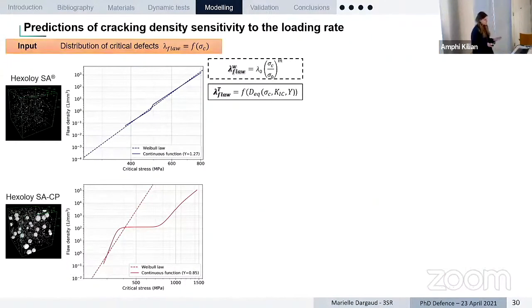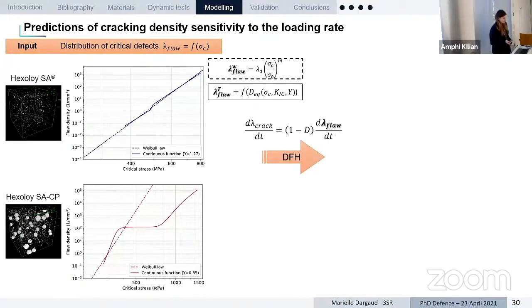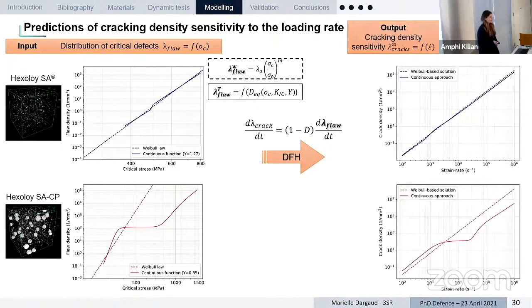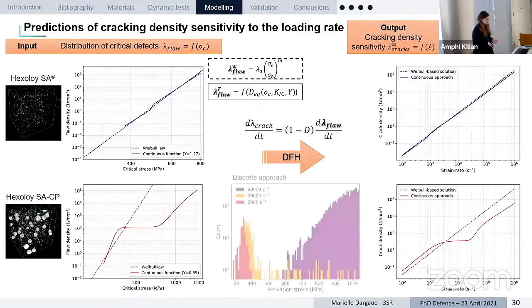Now, if we do the same to have the predictions of the DFH model, but for the cracking density, well, we apply this analytical formula with the evolution of the cracks in the material, and we can get the evolution of the cracking density according to the strain rate. What we can see for the first material, it's pretty much the same due to the same input data. And for the second material, we can see that we have a plateau which leads to a lower cracking density than what would be expected from the Weibull approach.